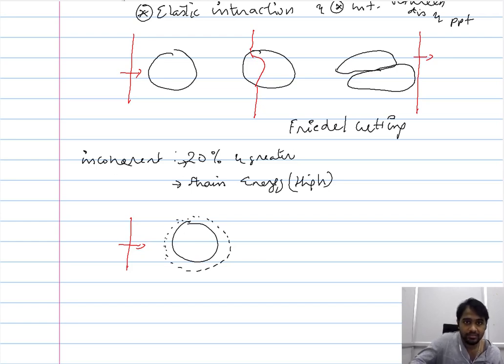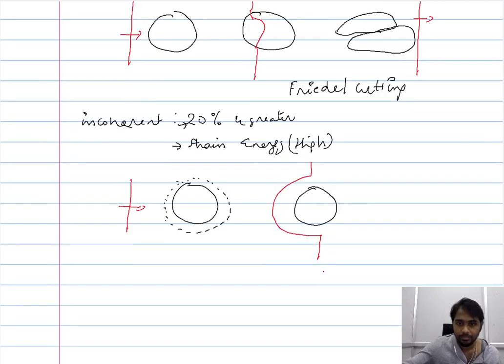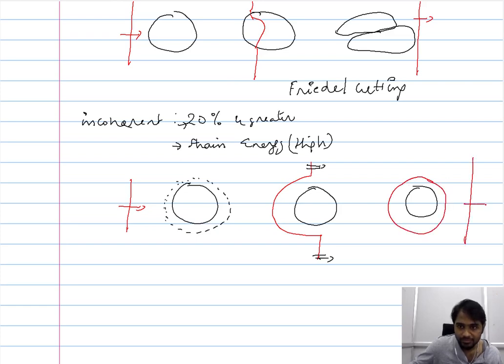So what it does is, the dislocation attempts to move around the precipitate. And finally, it moves away from this particular precipitate by leaving a section of the dislocation line around it, and then it moves. So it leaves behind a section of the dislocation around it.